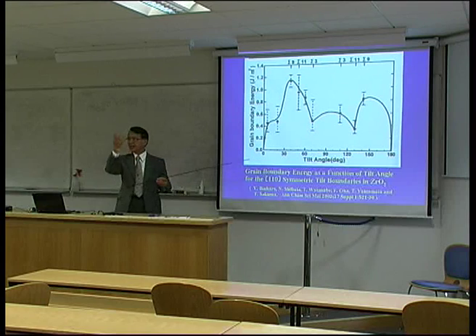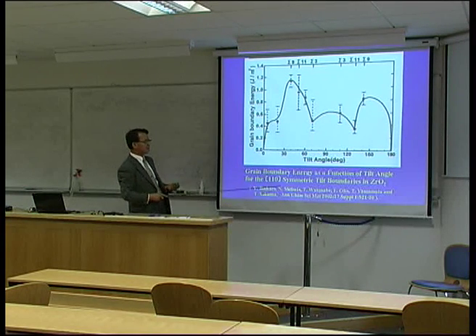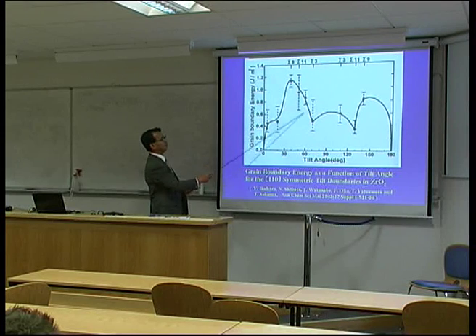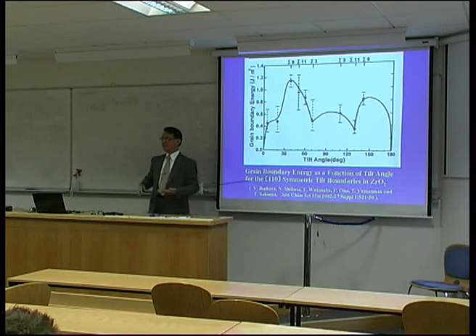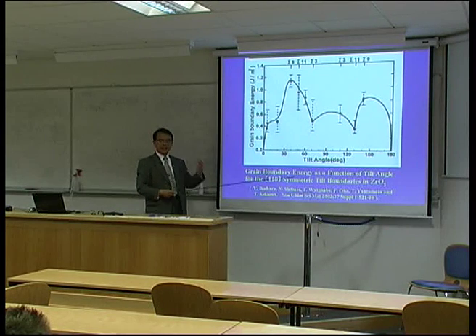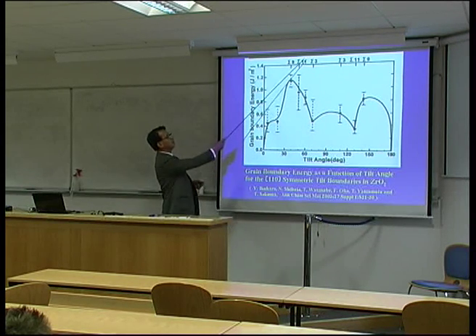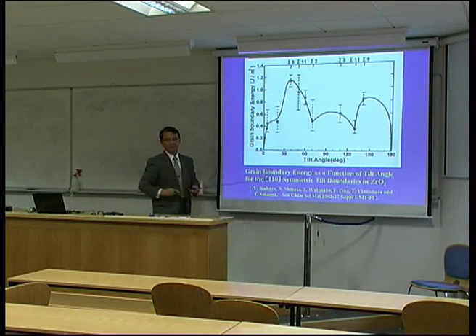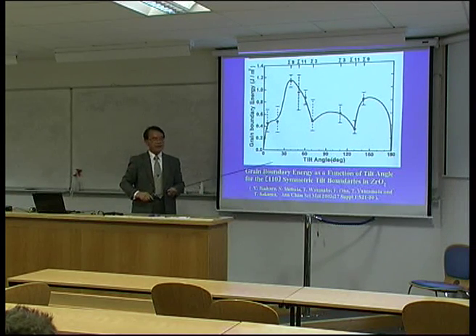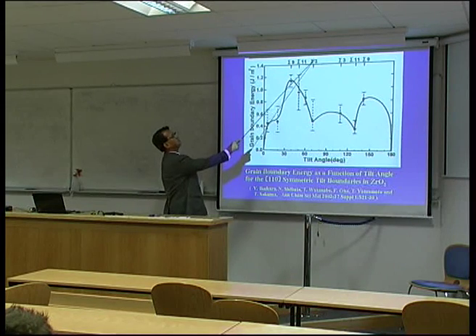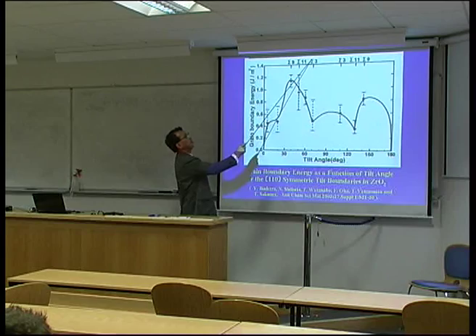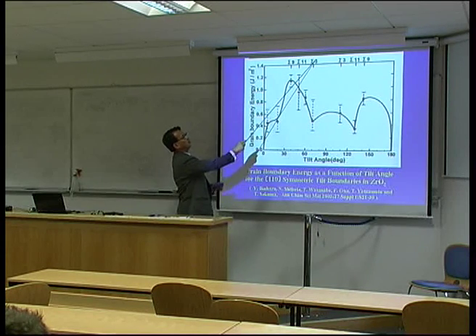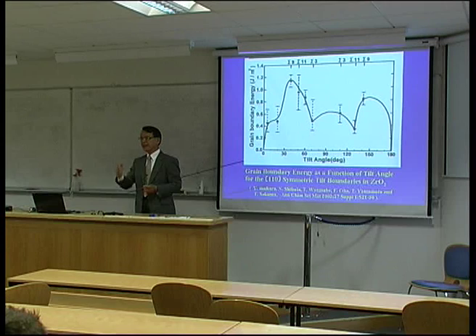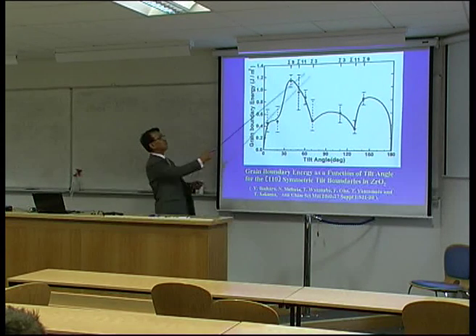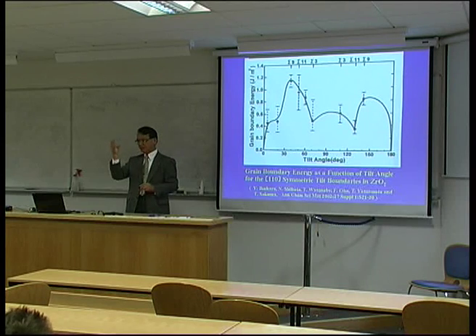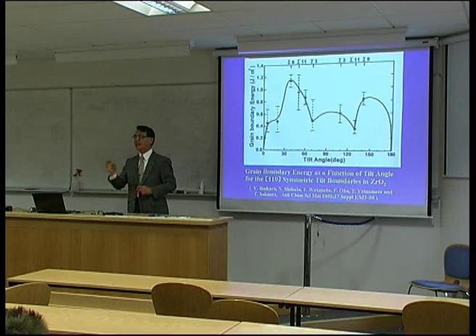In the case of a pure tilt boundary, in the case of a bicrystal sample, we can determine the boundary energy very precisely. But normally, in the case of metallic material, we define the coincidence boundary by sigma, the Greek letter sigma, and the number which indicates the degree of order. So with a lower sigma value, that boundary structure means a more ordered structure.